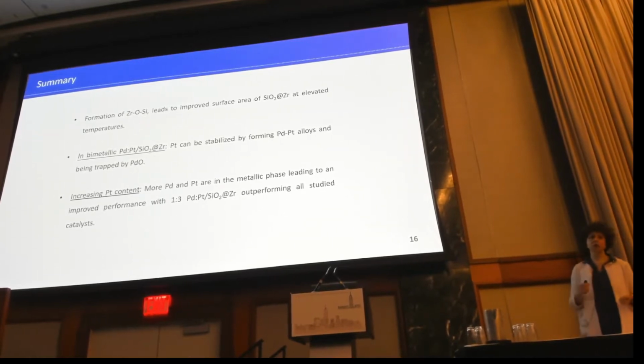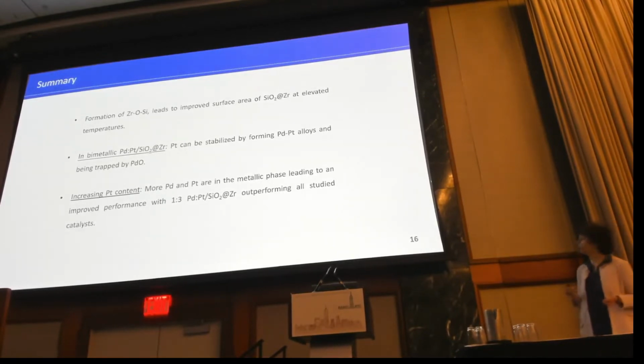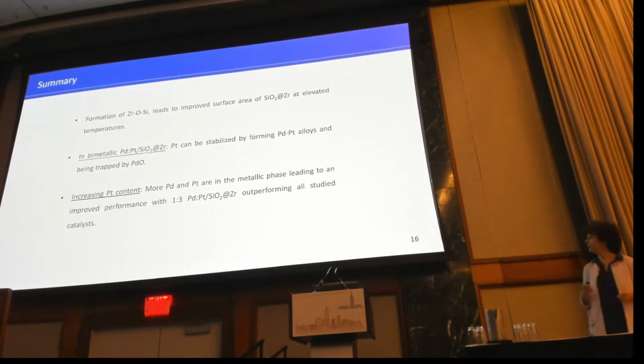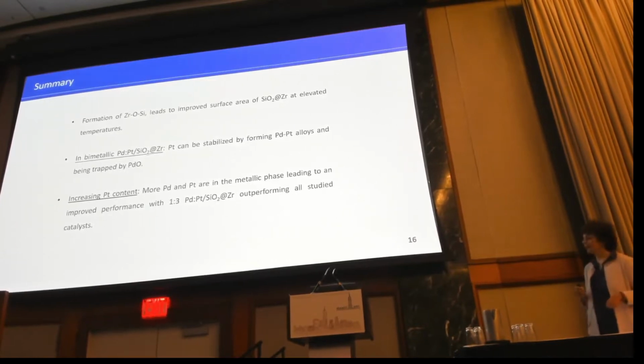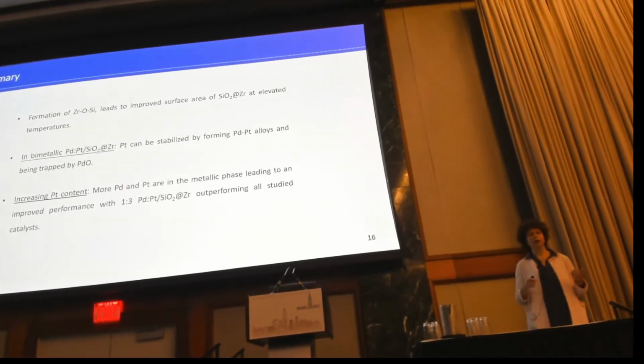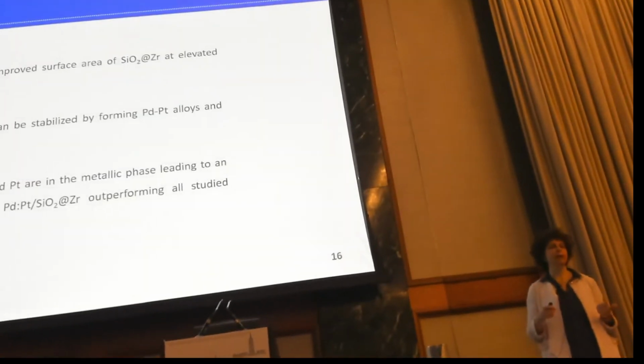So I hope I convinced you that on the silica zirconium catalyst there is a zirconium-oxygen-silicon bond that is formed, and this leads to improved surface area of this material when it's exposed to elevated temperatures. So when we have bimetallics, palladium and platinum, supported on the support, platinum can be stabilized by being trapped in the palladium oxide phase and also by forming palladium-platinum alloys. And when we increase the platinum content, we have more palladium and platinum in the metallic phase of the bimetallic particles, and this leads to an improved performance of the 1 to 3 palladium to platinum bimetallic catalyst.